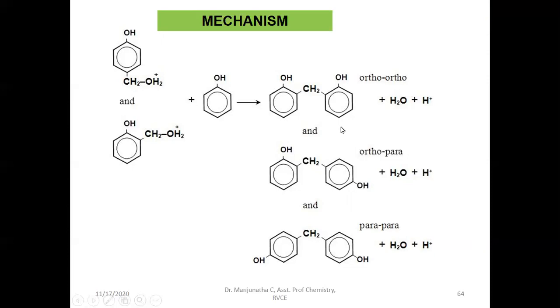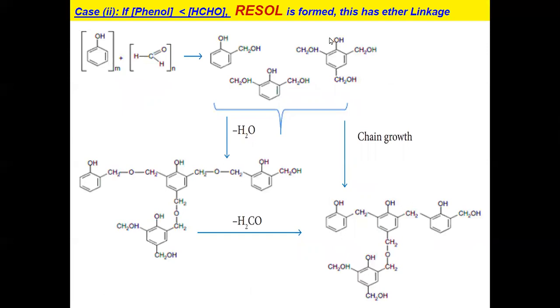The second intermediate polymer of Bakelite is Resol. That is another intermediate product formed when we take a lower concentration of phenol than formaldehyde. If formaldehyde concentration is higher, the same phenol forms bonds with a greater number of formaldehyde groups. Therefore, you get monomethylol, dimethylol, as well as trimethylol phenol — ortho and para trimethylol phenols are formed in this case as the first intermediates.